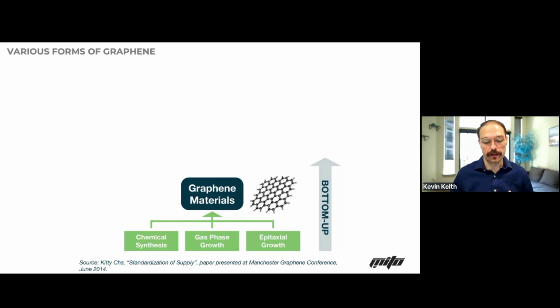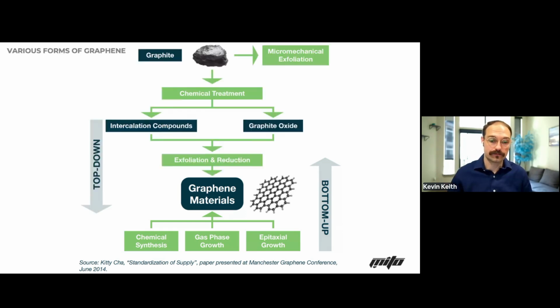Another method is what we call bottom-up. Bottom-up is when you can grow it, you can crack it, you can take waste streams and blow them apart. So think methane, CH4, acetylene. You can start doing really high temp processes on this to be able to blow it apart. And whenever that happens, the hydrogen forms itself, and then the carbon forms together. And when you crack enough of this, graphene forms. So this one has a lot of other interesting intrinsic properties as well that you get differently from other feedstocks. So no matter which path you take, you can still get to graphene, but we have to understand what form of graphene is really going to come out depending on what your input is and how you process it. It's like anything else in the world.